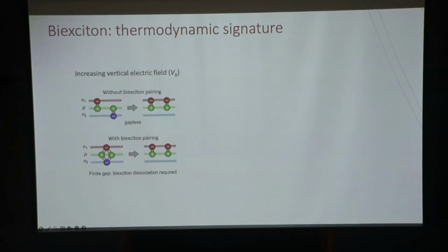But now, to know that we indeed form the bound biexciton state, we can again convert the density to the compressibility of the excitons. Let's say you have independent excitons, they are not bound. Then if you apply a vertical electric field, you can continuously switch one type of dipole to the other dipole with no energy band gap. However, if they are bound into these biexcitons, they will have a finite gap to polarize one into the other.